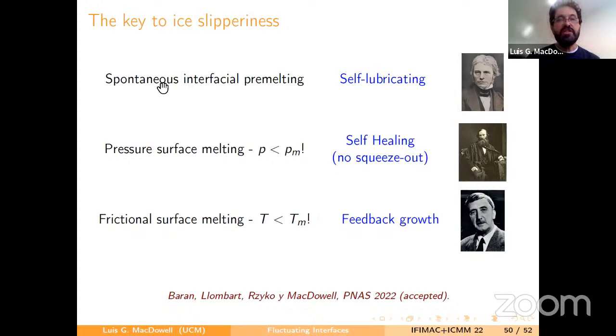Okay, and I think this summarizes some of the key features of ice slipperiness. First, we found that you have spontaneous interfacial pre-melting as suggested by Faraday. So that provides for self-lubrication. Now, if you compress the film, then you actually get an increase of the film thickness. So it's related to the hypothesis of James Thomson of pressure melting, but it's not quite pressure melting because the pressure is well below the bulk melting pressure. It's a surface phenomenon, okay? But it means that these lubrication films are self-healing, okay?